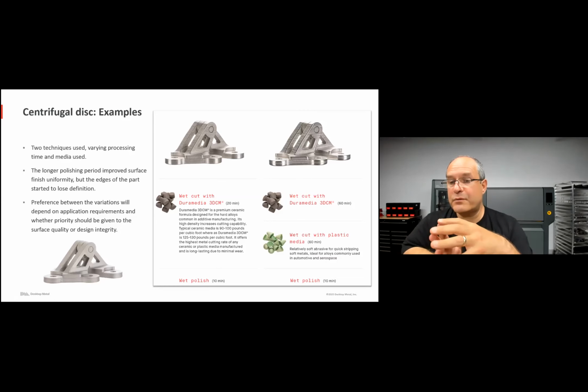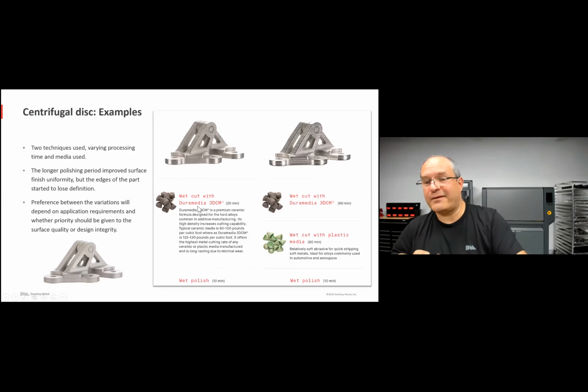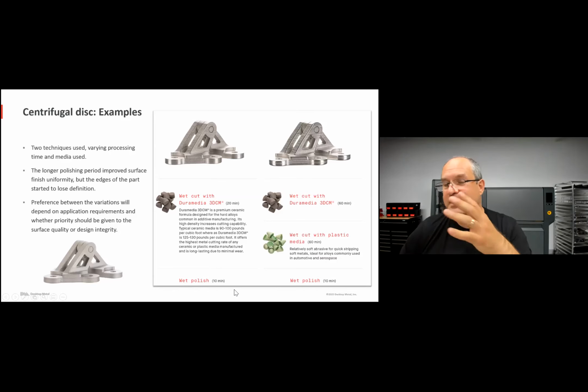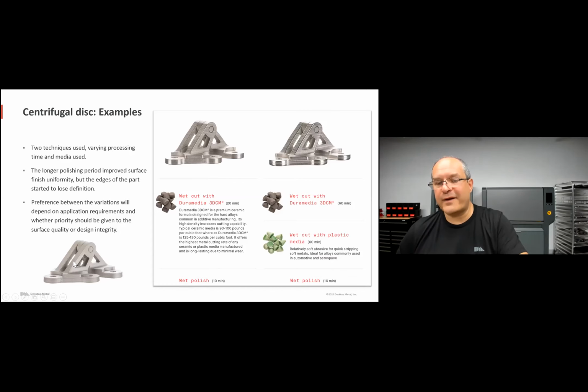And you can run with this kind of media for 20 minutes inside a centrifugal disc, and then a wet polish for another 10 minutes. So really, it winds up being a 30-minute process. And you go from this kind of rough and fairly matte process to a smoother and a shinier part.